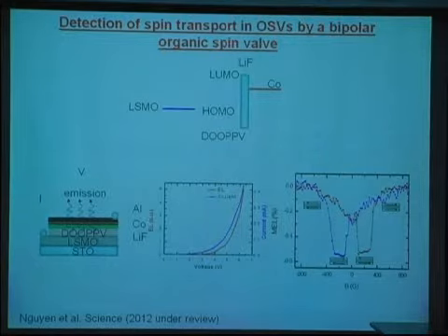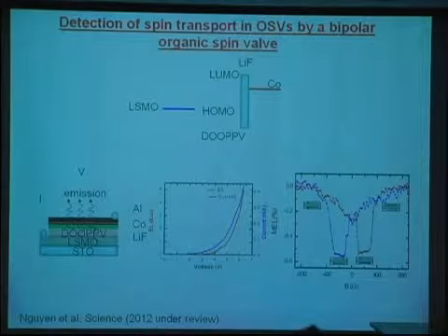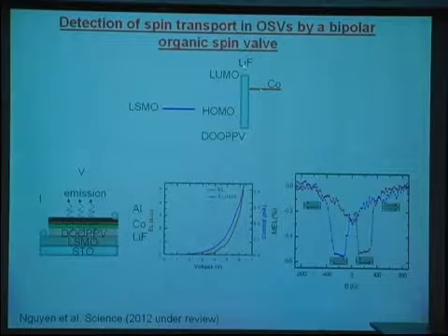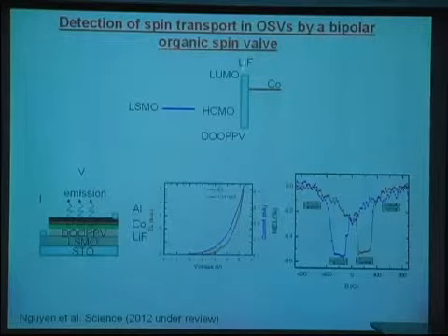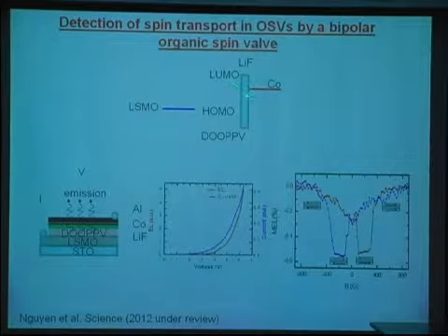So I'm just curious, if this is an insulator, then what is the work function in that case? How do I think of a work function for an insulator? And how does it modify the work function of cobalt? Just confused a little bit. Because of the polar nature, the dipole interaction between lithium fluoride and the electrons inside the cobalt somehow lifts up the Fermi energy close to the interface. This is just exaggerated. I should plot something like this. Yeah.